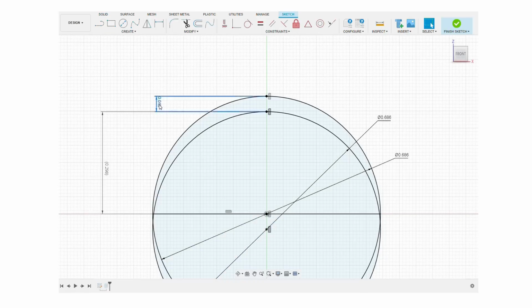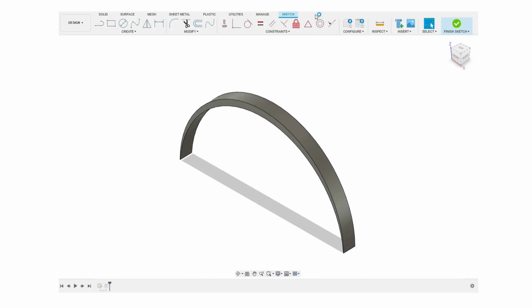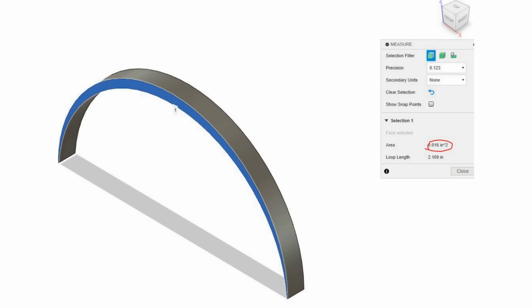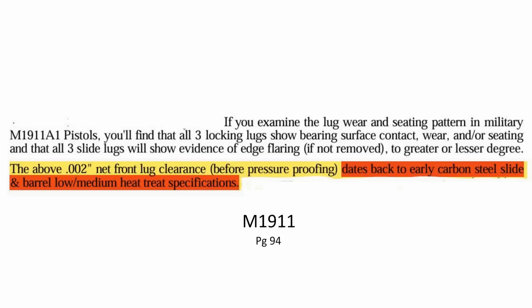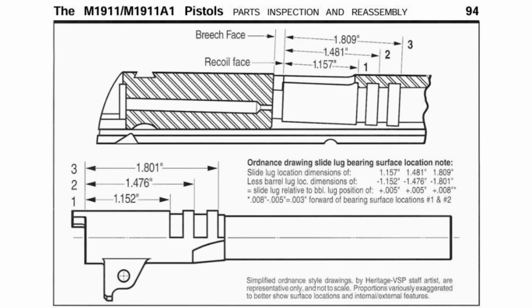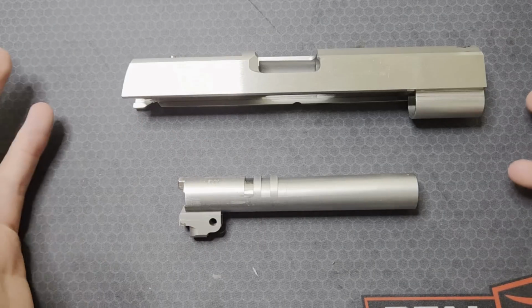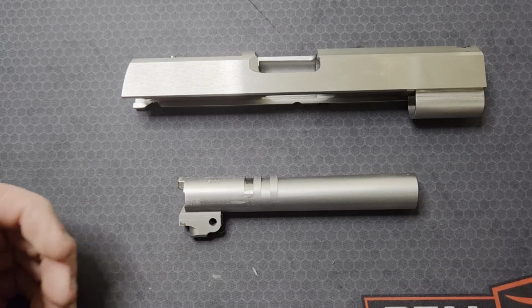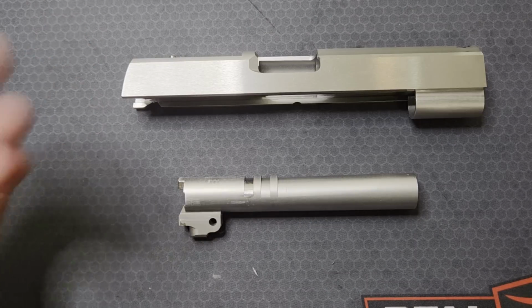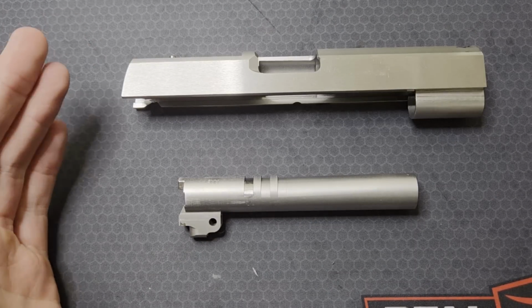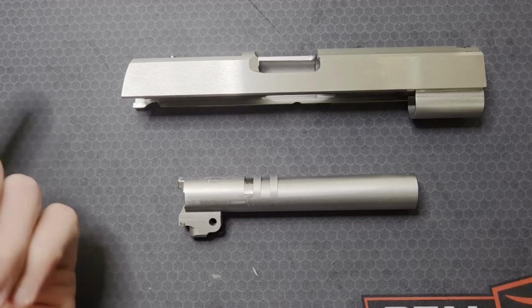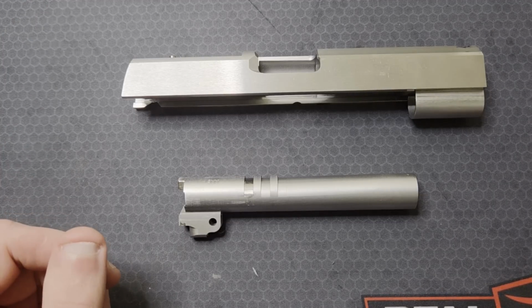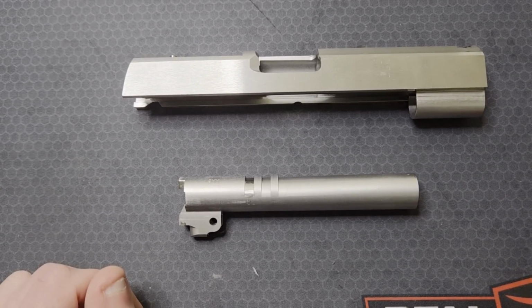However, if 2 lugs were contacting, each would need 24 thou of engagement. That's only 45% of minimum slot depth. So there would be plenty of margin for lower yield strength materials while still maintaining that 2-to-1 safety factor. We can also probably assume that the design was intended to have more than one lug in contact, being that there's 3 of them. This was kind of a nice little gut check that my values with modern alloy carbon steel weren't unreasonable. I hope you were able to follow along with that calculation and it made some sense. I hope I explained it well enough and that my assumptions and the 2-to-1 safety factor I included seem reasonable to you. I am feeling good that the value I calculated is close to other values I've seen from multiple sources. If it was like 10 or 80 thou, I would know that I screwed up. All right, sorry about that. Back to the process.